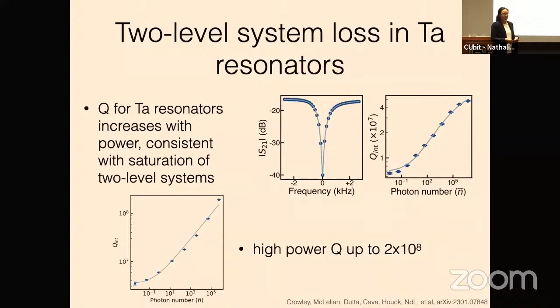I bet it's not two-level systems because it just seemed too easy, but it's all two-level systems is going to be the punchline. So what we can do is just a transmission measurement through one of these resonators. And we see this very two-level system-like behavior where the quality factor of the resonator saturates with increasing microwave power.